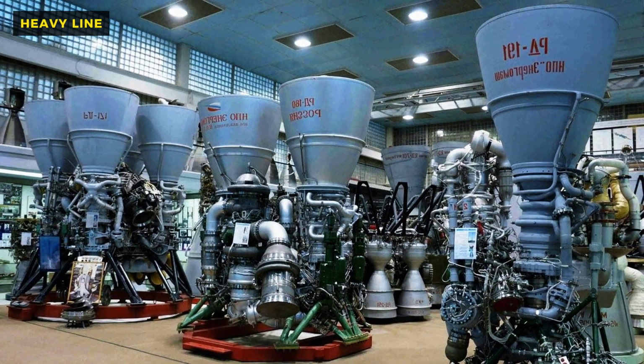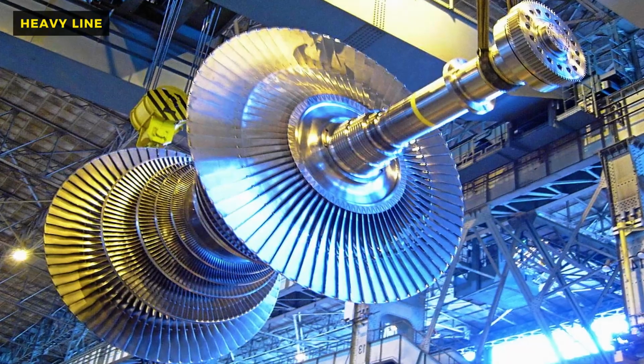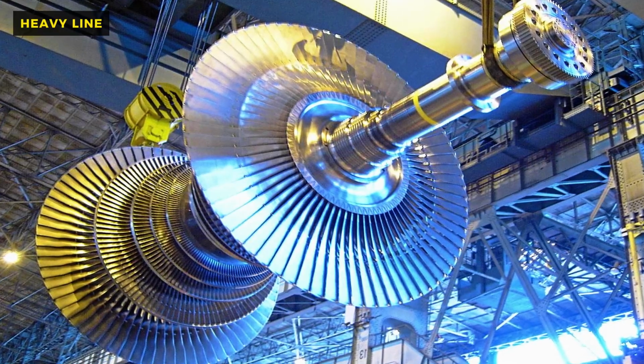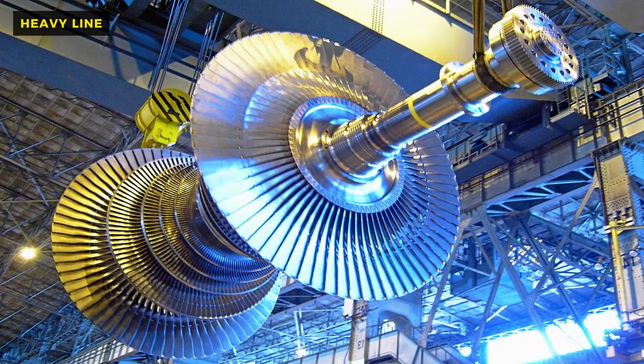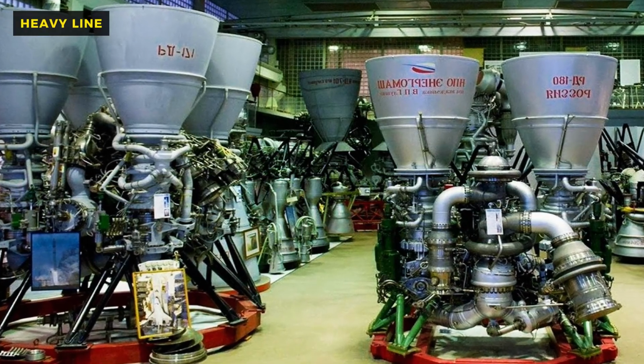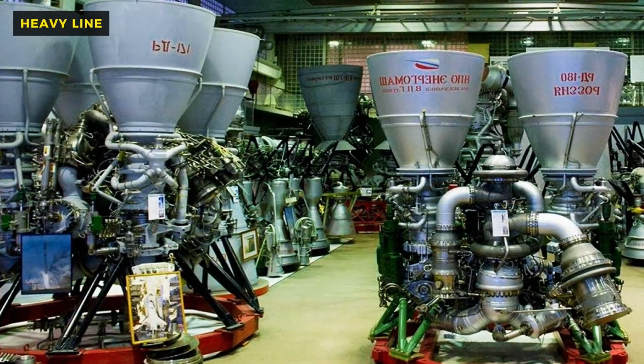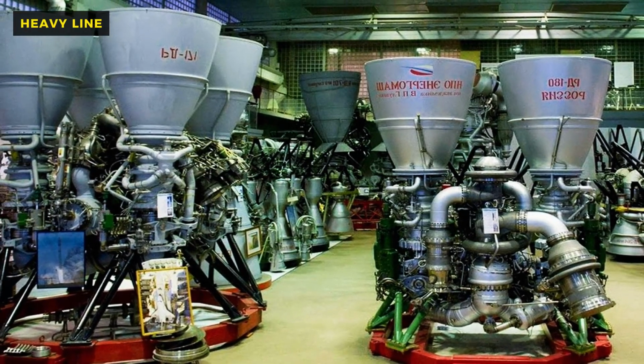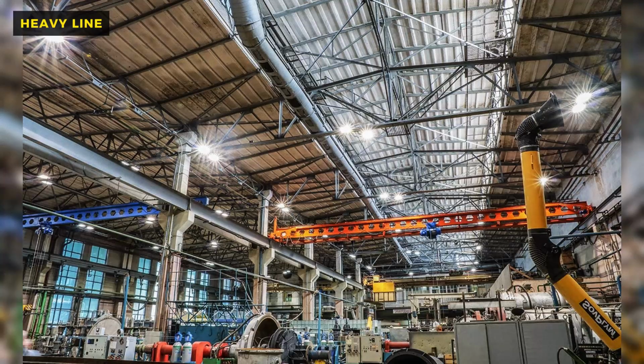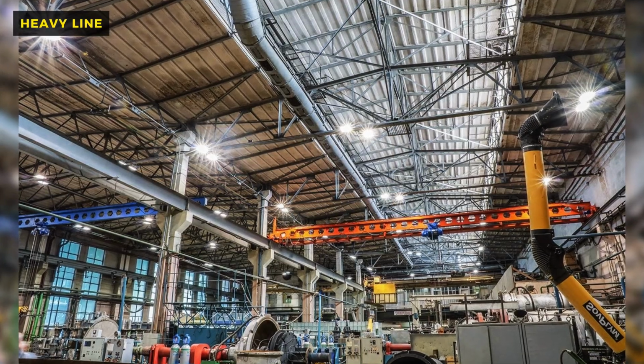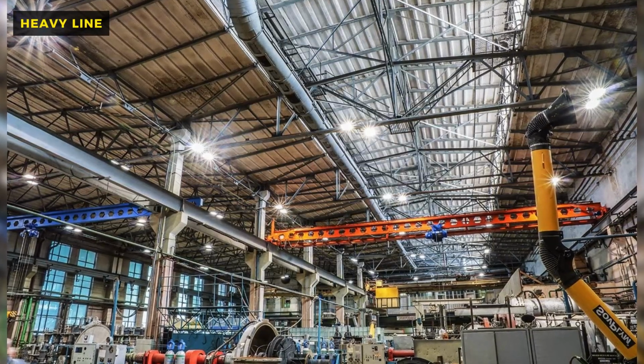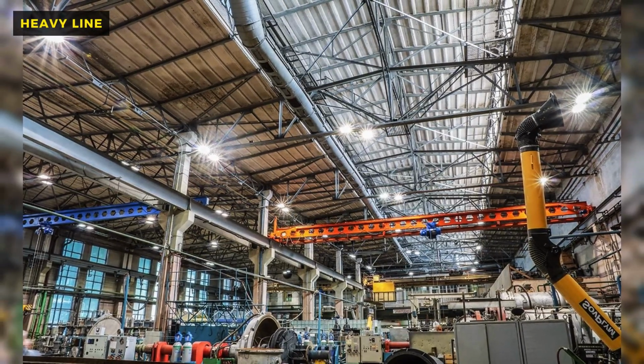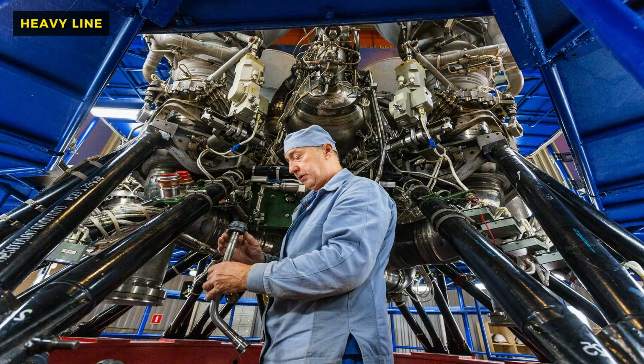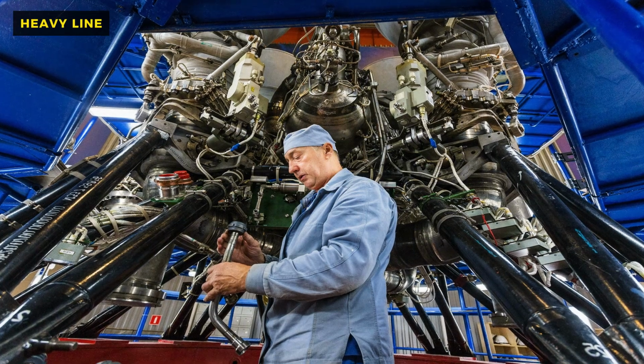It is incredibly hard, remarkably thin, and it is the only thing standing between the soft, vulnerable core and the destructive environment outside. If that oxide layer cracks or flakes off due to vibration or thermal shock, the oxygen will attack the exposed fresh metal instantly. The result is what engineers call a burn-through, but that clinical term fails to capture the horror of a catastrophic engine failure where the high-pressure gas acts like a plasma cutter, slicing through inches of steel in a fraction of a second and turning the entire engine into a bomb.